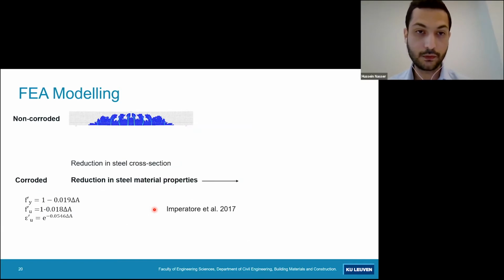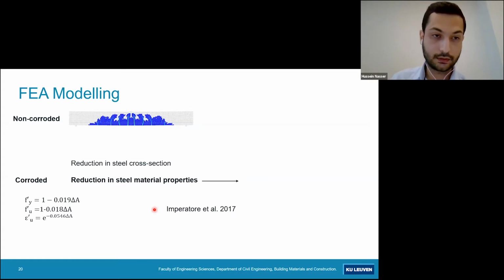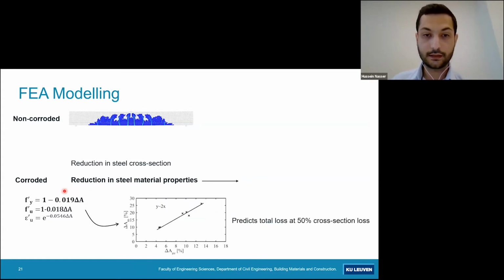It's not enough to, let's say, know the cross-section loss, but corrosion also deteriorates the steel material properties, namely the yield strength, the tensile strength, and also the ultimate strain. I used the model from the literature with the reduction factors shown to the left. If I would justify the use of these reduction factors, I found that at some points along the rebar, the maximum cross-section loss reached is double of that of the average.